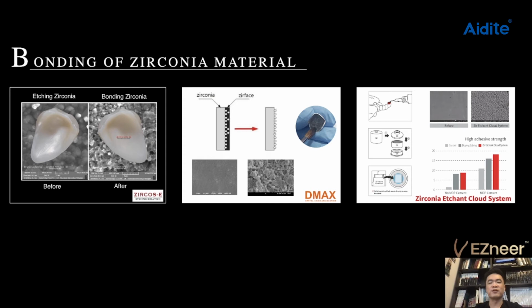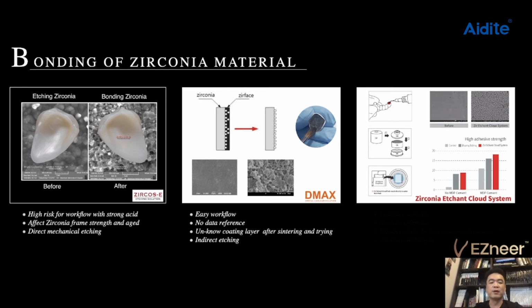the bonding technique, maybe like ZIRCOS-E. They use a very high percentage of acid to etch the Zirconia, but it also has another problem, because this is a high risk for the workflow, because this is also dangerous. And after the etching, the Zirconia frame may decrease in strength, and also affect a few Zirconia properties.